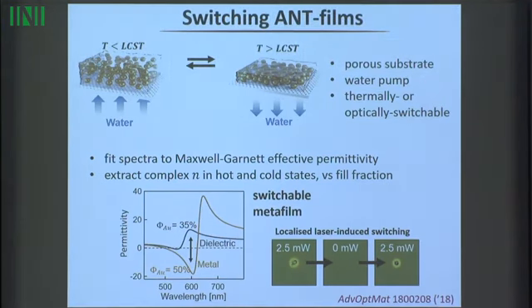And so this can work very fast. We can also use this system, I mean, actually the water gets sucked in if we cool it slightly, a few degrees, and if we heat it a few degrees, the water gets pushed out, and we can analyze what's going on here to understand what the effective parameters of this material are. So for instance, the permittivity, essentially the refractive index squared, in this spectral region here, goes from being something that looks like a dielectric, say a glass, a colored glass, to something which is metallic. And you can just switch directly backwards and forwards between these two states. So everything changes when you switch between those states. And again, we really don't have any way of predicting what it is we're going to get in this system, because the coupling is very strong.